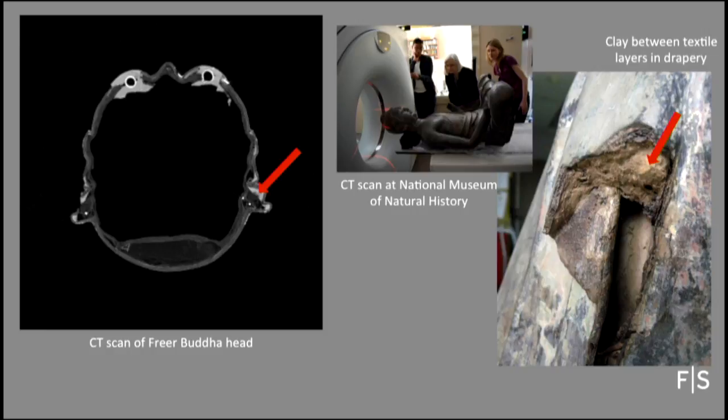Only the Bodhisattva head still contains accessible clay clinging to the interior of the face, in the recesses of the lips, chin, and nose. A sample revealed it to be a gray, tan, unfired clay of fine texture. The clay was uniform in particle size with no added organics visible in the SEM photos. However, a large carbon peak present in the EDS spectra was later identified as lacquer, which was probably used to adhere the textile onto the clay.